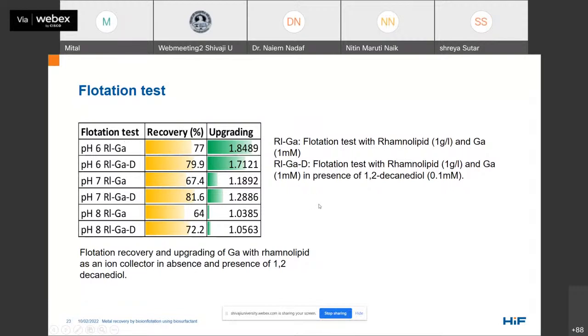I have not included the recent results here where we did flotation experiments of gallium for selective recovery in the presence of other metals like arsenic, because we want to apply this flotation process for recovery of gallium from the gallium arsenide industry, which has more arsenic as compared to gallium. And our recent experiments have shown that we can recover gallium at higher concentration very selectively as compared to arsenic.